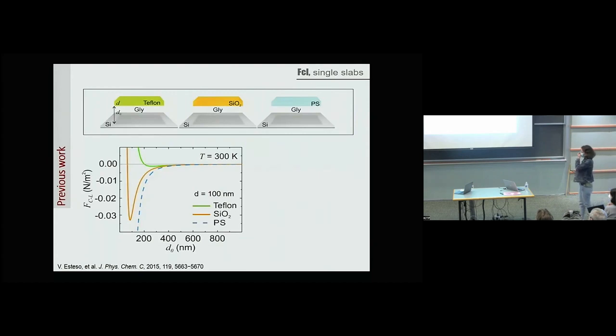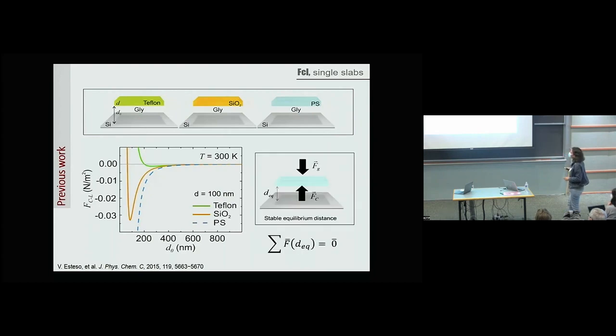So what we found at that time is that thin films of, theoretically, thin films of Teflon, silica, and polystyrene immersed in glycerol over a silicon substrate could levitate. Here I plot the Casimir force, but the total force, just shift this a little bit. So anytime the total force is 0, your system is levitating. We find that for silica plates, this equilibrium distance is stable because you have repulsive Casimir forces at short separation distances, which is here, and then gravity, in this case, brings the system to the bottom, no?